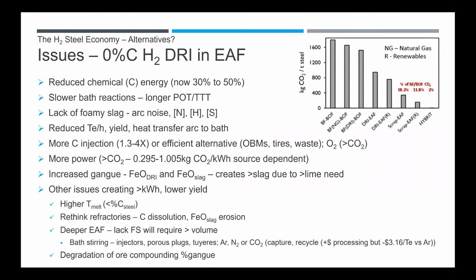More power is going to cost us between 0.3 and 1 kilograms of CO2 per kilowatt, depending on the source, hopefully green, but in the US, it's going to be an issue getting green power. Increased gangue will come from not only the DRI, but also the FeO going to the slag, and that's going to create more slag because of lime needs.